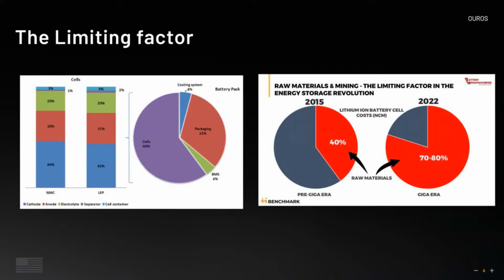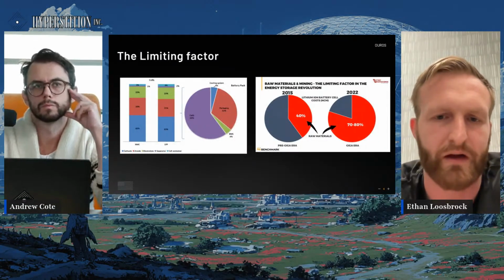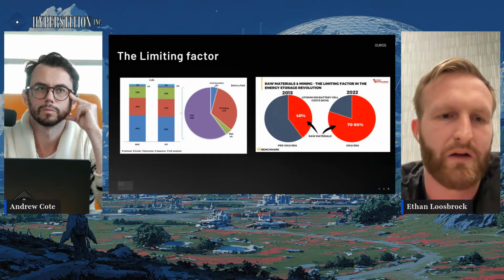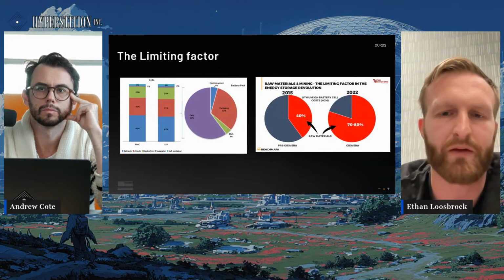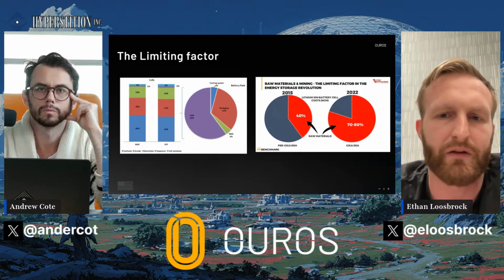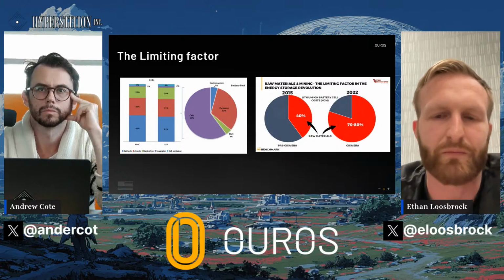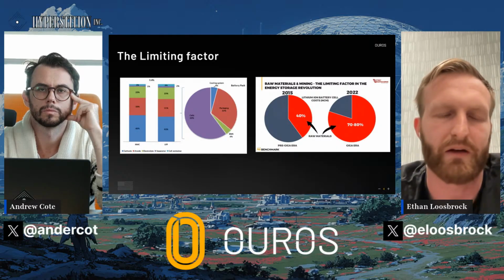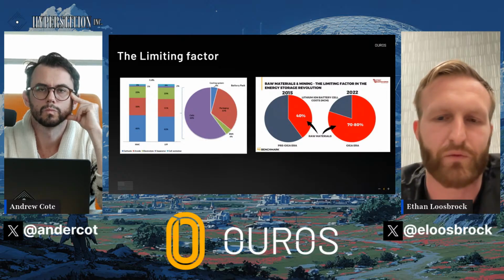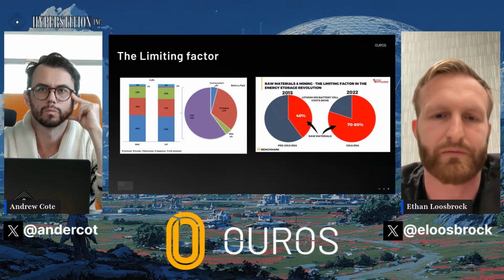So that's what this right graph is showing. We started at, the materials costs were about 40% of the cost of cells back in 2015, and then by 2022, the raw materials costs were 70 to 80%. Today, it's even higher, above 80% now. Once materials cost is the dominating factor of the cost of your device, you basically have to switch materials if you want to get any improvement, or try and squeeze efficiencies out of the materials you're currently using.